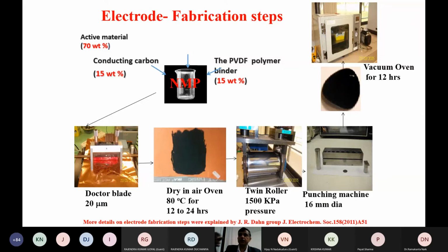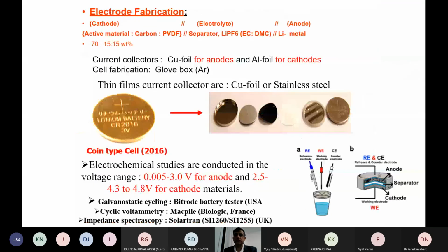So at the end, once you get the material, depending on the applications, pick the material. Now your material is ready. The usual practice is that you take 70% of your material and 15% conducting carbon, and PVDF as a binder to make a nice contact. Finally, by using the doctor blade, or you can take a small glass slide, you can coat the sample on either copper foil or aluminum foil. Then dry in the oven and we can roll it. It's very important to make a nice contact, that's why we use a roller. Finally, punch into 16 mm diameter electrodes, put them in the oven to dry, and you can use them for coin cell fabrication.